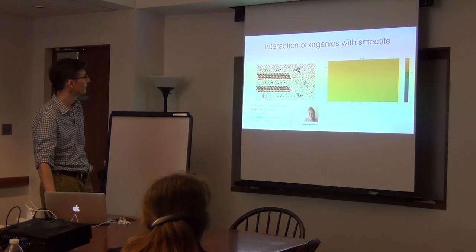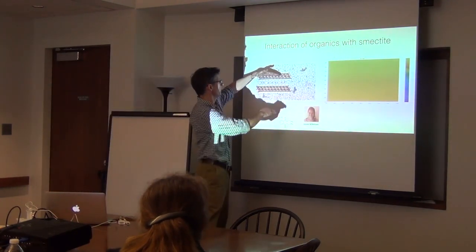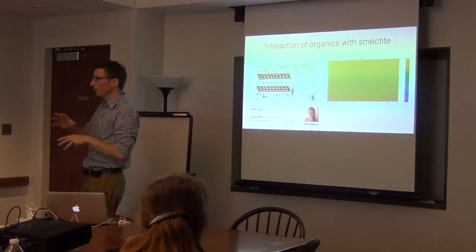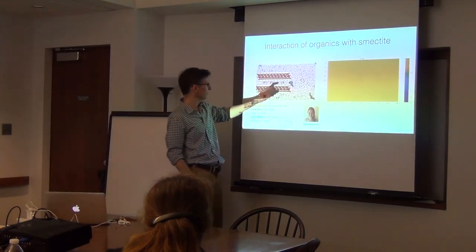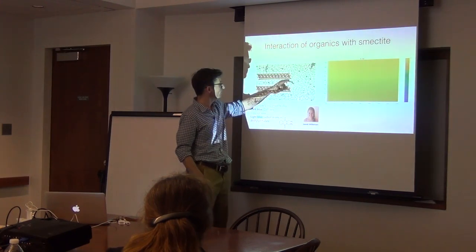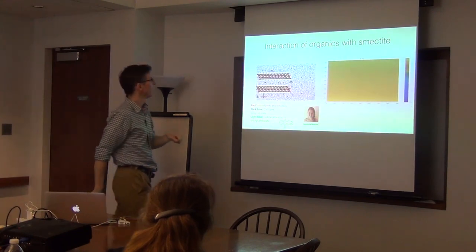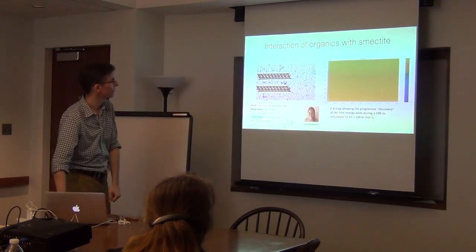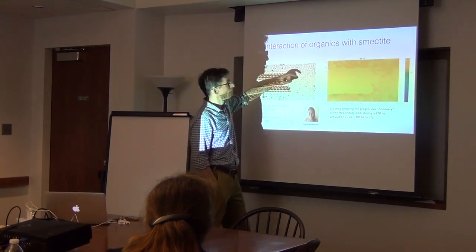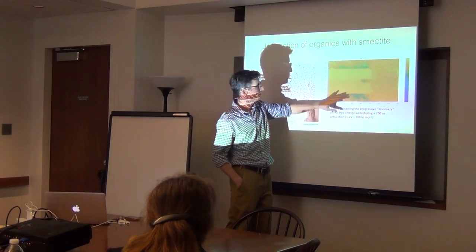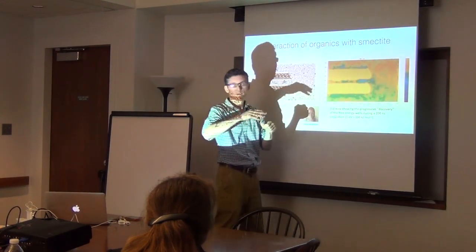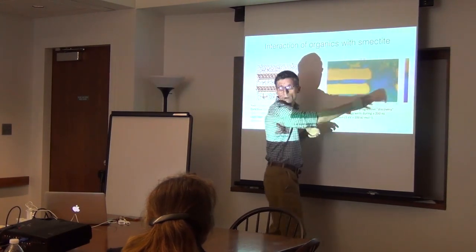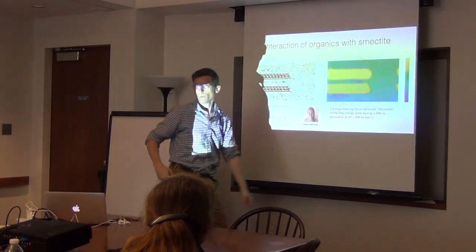The last thing I'm going to mention is simulations with two mini smectite particles with calcium ions, where we add in a few molecules of organic contaminants and look at whether or not they absorb on the surface. If we run a standard MD simulation, the organic contaminants just stick to the surface and never detach. So again we're using MetaDynamics to force the molecules to explore the entire landscape and tell us the shape of the free energy landscape — this is showing over 200 nanoseconds how the code finds the free energy minima, and it finds that it's favorable for the molecule to be near the surfaces. From the free energy difference of about 100 kilojoules per mole, we can calculate a Kd, an absorption coefficient.